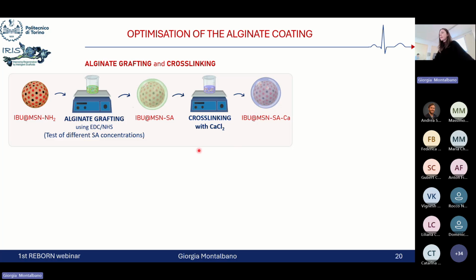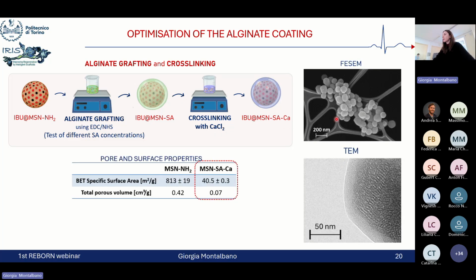At this stage, as a final step of the protocol, we immersed our ibuprofen-loaded nanoparticles into an alginate solution, where we exploited carbodiimide chemistry to activate the surface, and where we also tested different alginate concentrations in order to obtain the best performing coating. Then we induced the cross-linking of the polymeric coating using calcium chloride. Here, these images confirm the successful coating of our particles, registering a slight increase in the final dimension of the nanoparticles. The TEM images also show the creation of this thin polymeric layer on the mesoporous structure of the silica nanoparticles, and physicochemical analysis shows the drop in the specific surface area and the total pore volume after the application of the coating.